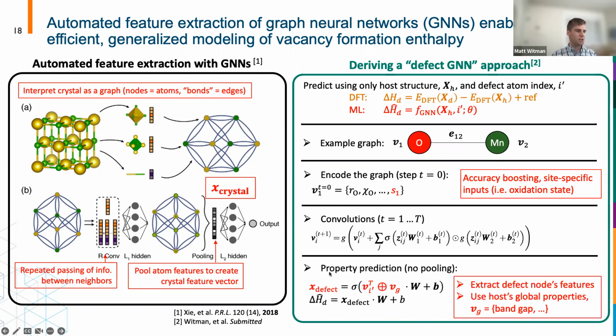So then the thing that you need to do in order to predict defect formation enthalpies is, instead of doing a global pooling, you just do a node level prediction in your graph. So you basically just take out the node that should be defected at the end of the convolutions. We actually concatenated that with some of the other global host properties like band gap, effective electron mass, and things like that. And then you pass that quantity through any final feed-forward neural network layers, and that gives you this relaxed defect formation enthalpy. So all you need is the host input geometry. You tell it which node is going to be defected, and you get out the relaxed defect formation enthalpy.